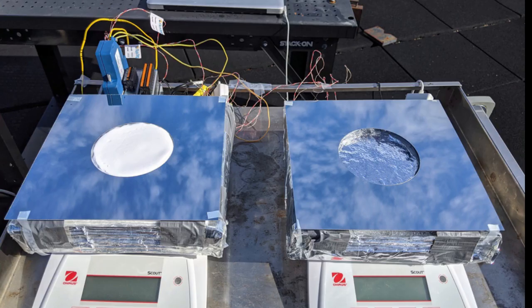The novelty here is really just bringing together the radiative cooling feature, the evaporative cooling feature, and also the thermal insulation feature, all together in one architecture. The system was tested using a small version just four inches across on the rooftop of a building at MIT, proving its effectiveness even during sub-optimal weather conditions and achieving 9.3 degrees Celsius of cooling.